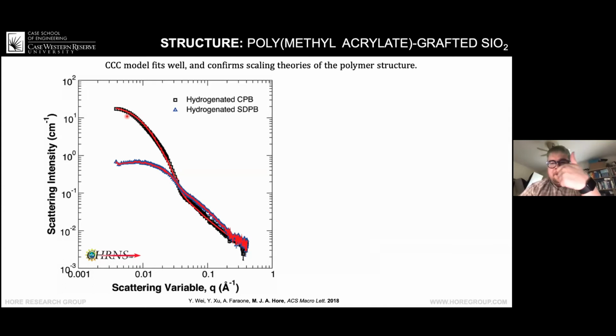So the diameter of the core is fixed because we know that. We know the grafting density, so we know how many polymers there are. We know the molar masses of the polymers and the different blocks of the polymers. We know the Kuhn length and things like that. So really, the only thing that we're fitting here is the value of RC when the brush transitions from a concentrated to a semi-dilute region. The sizes, the radius of gyration of both blocks, and then the Flory exponent of both blocks.